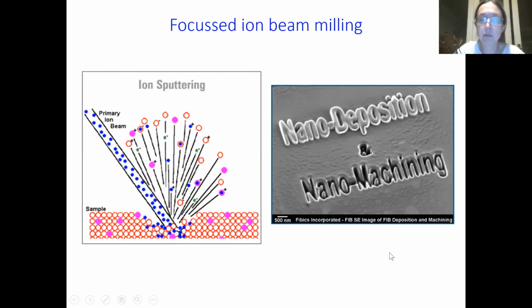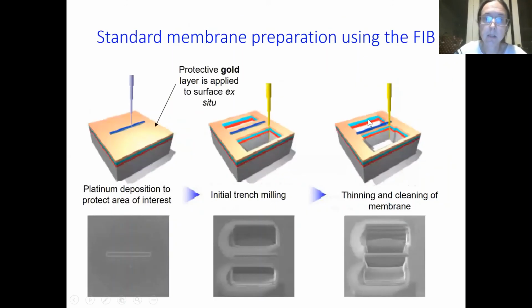I'm going to show you a very brief run through of what we do. This is actually quite a well-known technique for making samples to go into the TEM, which tend to be thin foils, like thin wedges, effectively. There we do a platinum deposition, make a sort of platinum square on the surface to help protect the bit of the sample we actually want to look at.